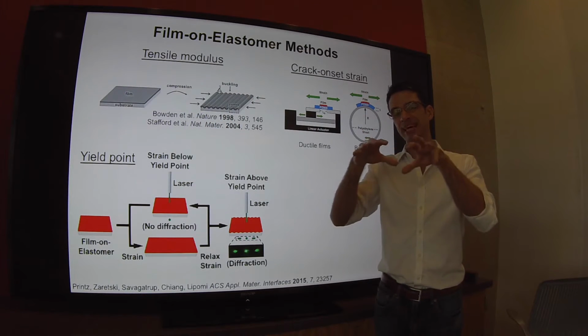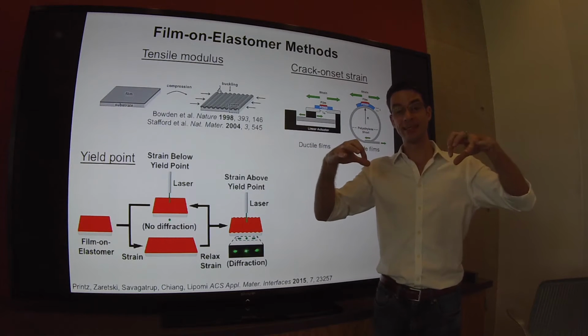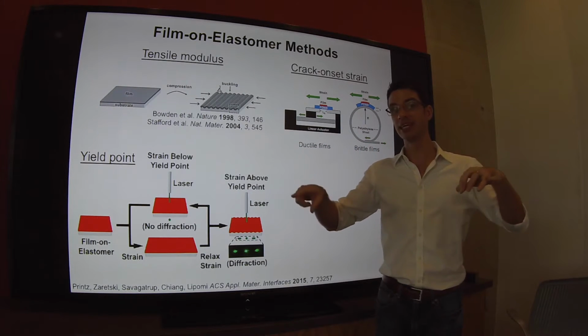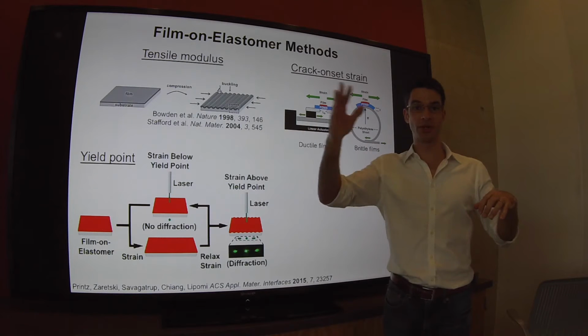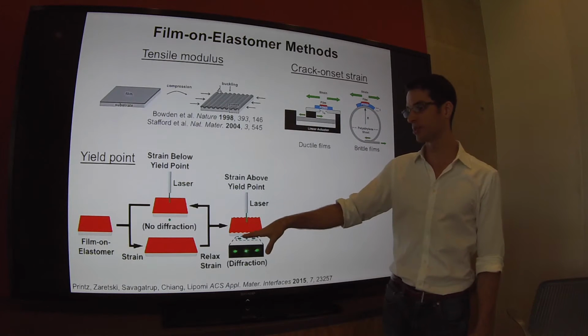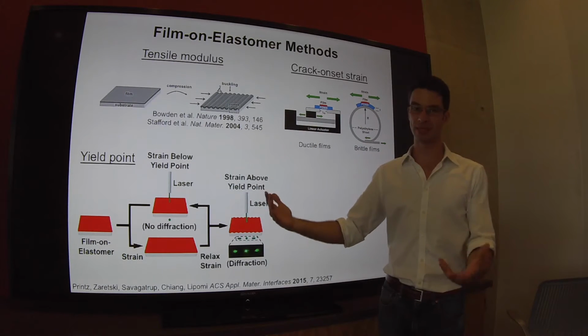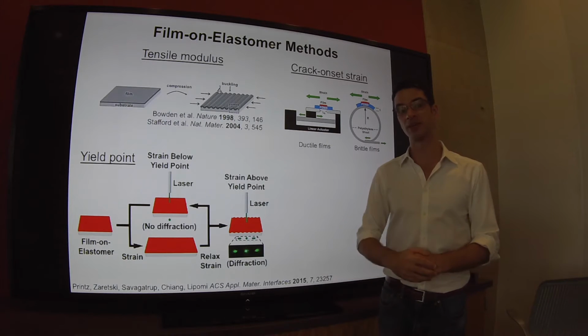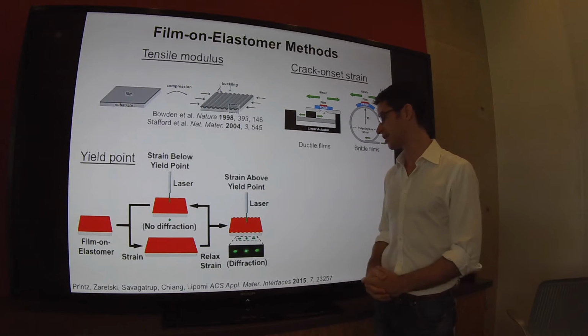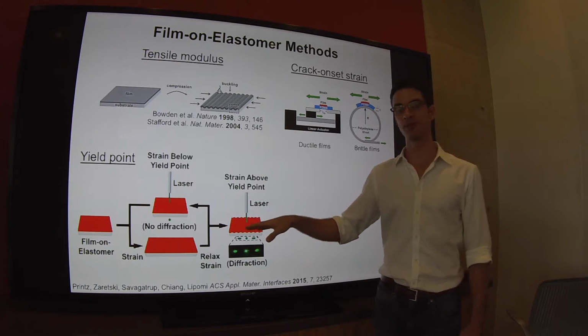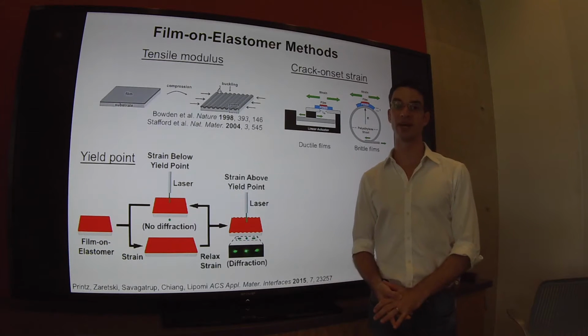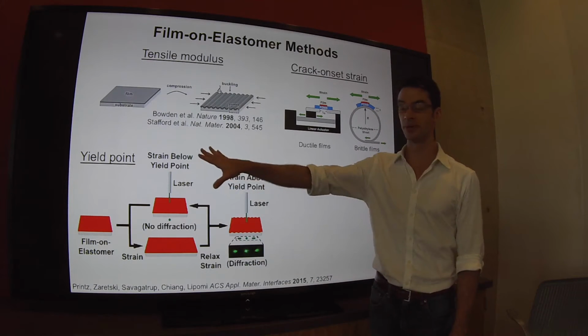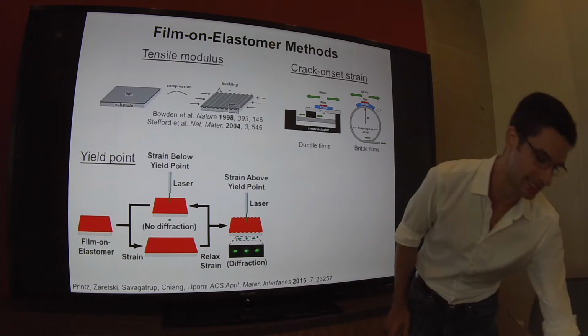Now, as soon as that film experiences plastic deformation, the film will buckle when it's returned to 0%, and you can observe the buckling optically. But sometimes optical wrinkles are difficult to detect by microscopy, so you can shine a laser through them and detect the diffraction pattern on a screen, and when you see that, you know that the film has surpassed its yield point.